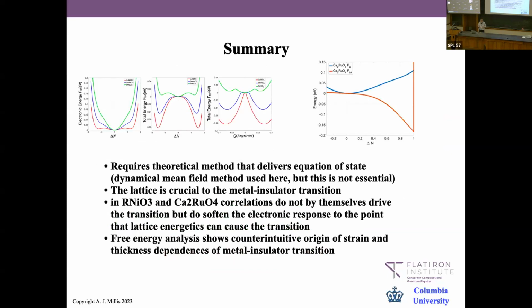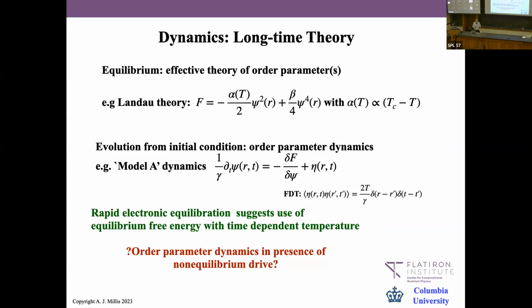Okay, so now let's ask about dynamics. If I start with the analog of what Ian Fisher did, I could take some kind of Landau theory order parameter. I could say I have several order parameters with different coefficients, and I can impose a dynamics. Just for the sake of doing something, let me impose what's called model A dynamics, which is just relaxation. So we have an overdamped order parameter with an equation of motion which says that with some relaxation time, the system wants to relax to the minimum of the free energy. And if you're going to write an equation of motion, you also need a noise term whose magnitude is controlled by the fluctuation dissipation theorem. So this gives you a stochastic, nonlinear differential equation for your order parameter, and you can use this to discuss dynamics.